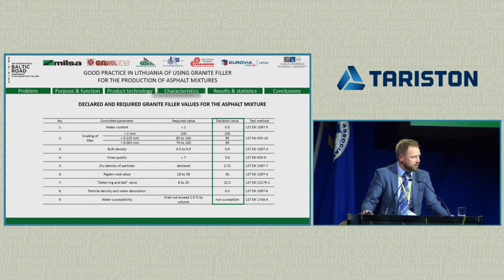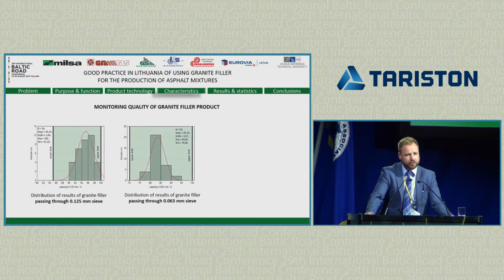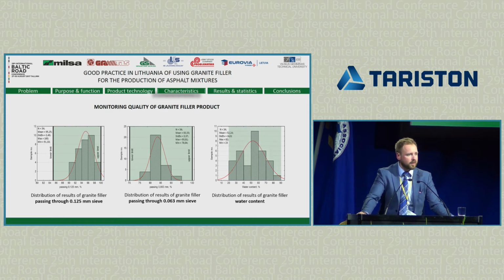Here you see declared values of parameters of granite filler. Actually, it all satisfies the requirements for asphalt mixture mineral filler. And to show you the stability of production, I put some histograms of, in my opinion, the most risky values, whose results have the biggest frequency during the production processes. So it is the passing through 125 micrometers, passing through 63 micrometers, and water content. So as you see, they are strictly within the requirement limits.